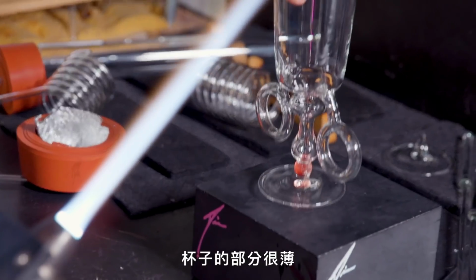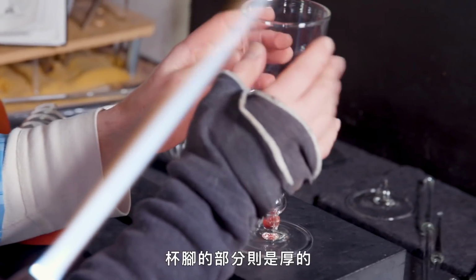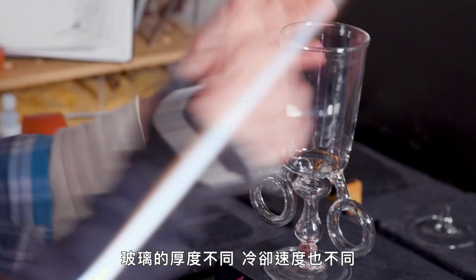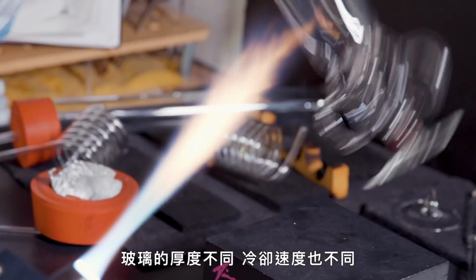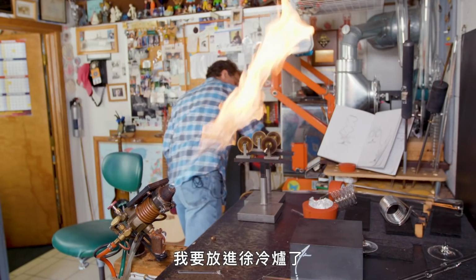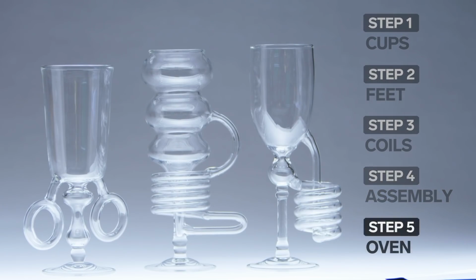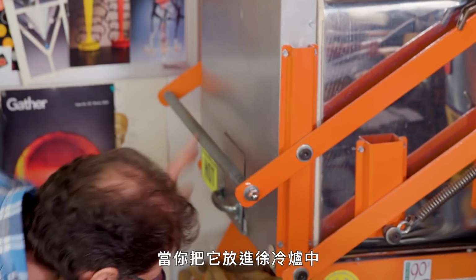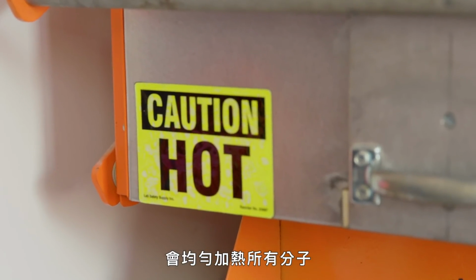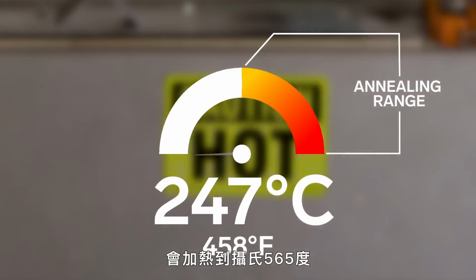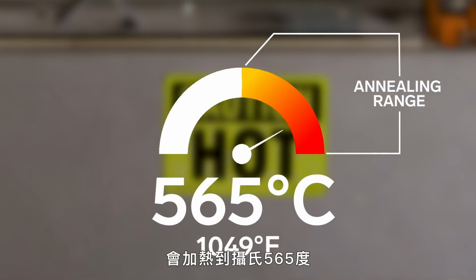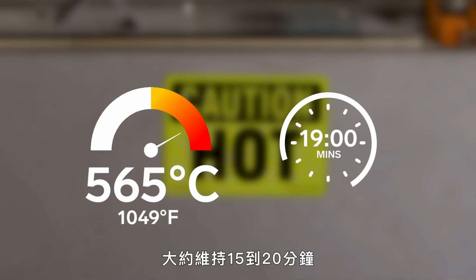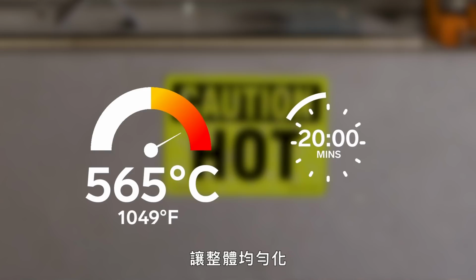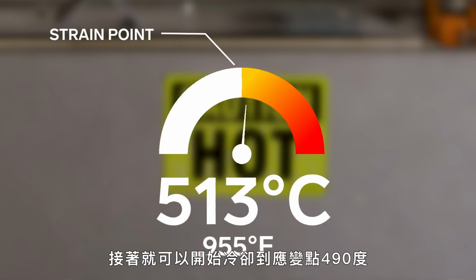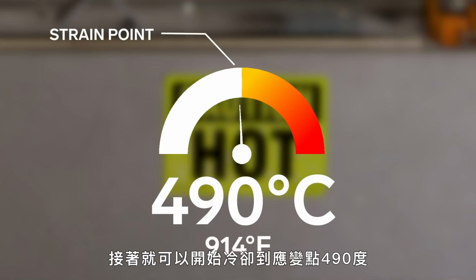After I've worked it, there'll be really thin spots on a cup and then a real thick spot down by the stem, because the glass is cooling at different rates when it's thick and thin. I need to go in the oven with it now. When you put things in the annealing oven, they heat up all the molecules evenly and it cools them all back down. So it heats up to 565 degrees centigrade and I hold it for around 15 to 20 minutes to allow everything to equalize. And then you can cool back down through the 490 temperature range, the strain point.